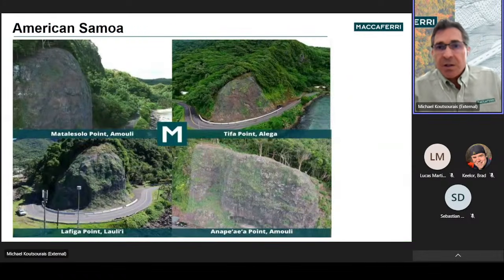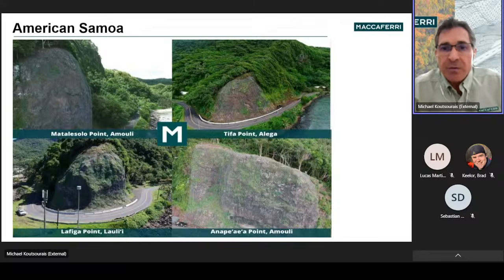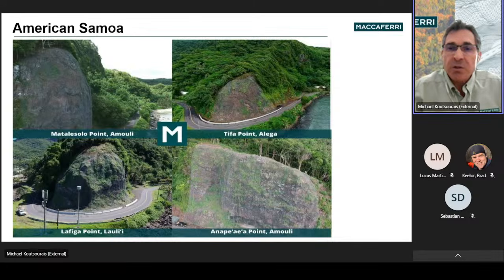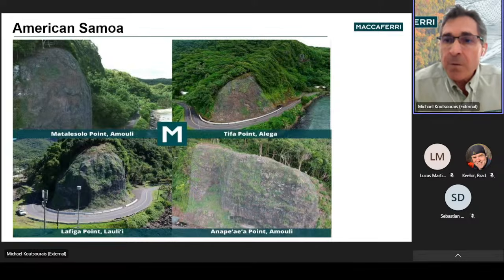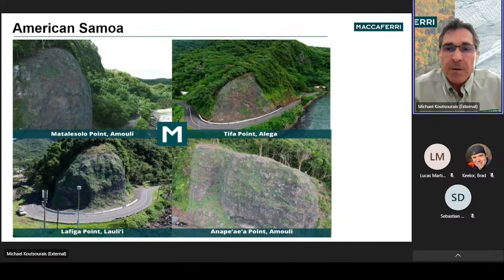This project is along the southern coast of Tutuila Island in American Samoa. The steep coral cliffs off the coastal highway had significant history of rockfall. The simple drapery solution included approximately 135,000 square feet of Maccaferri SteelGrid HR30. The near vertical cliffs ranged up to about 150 foot high on these 4 sites.